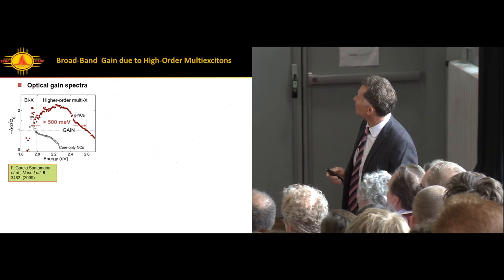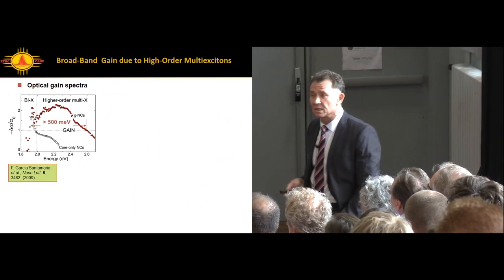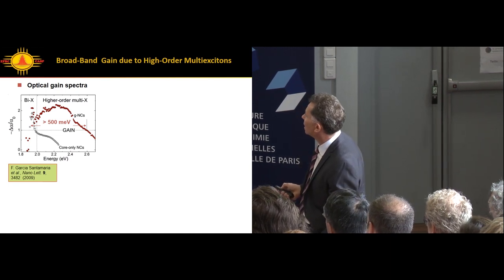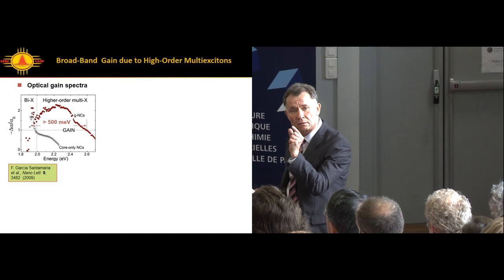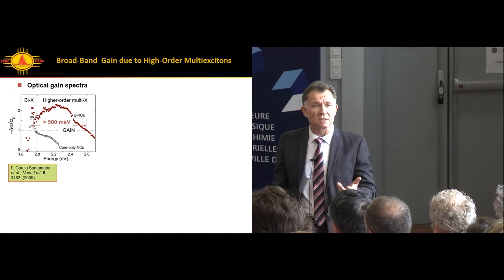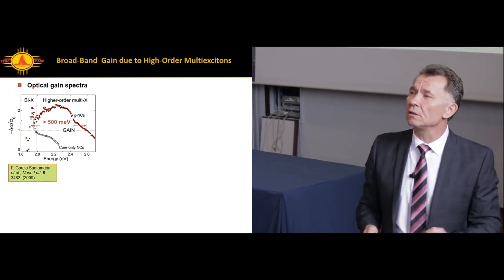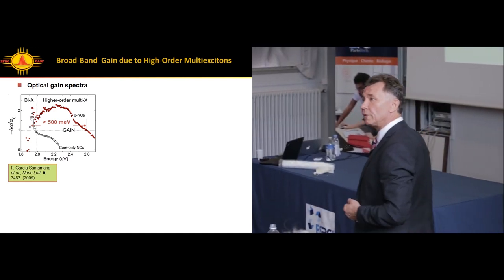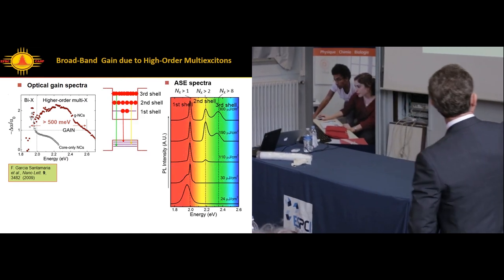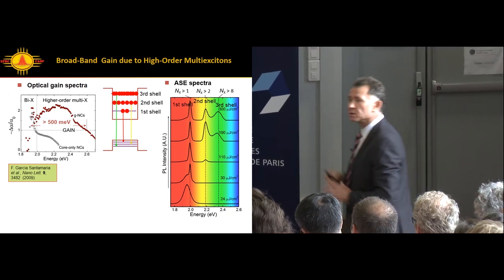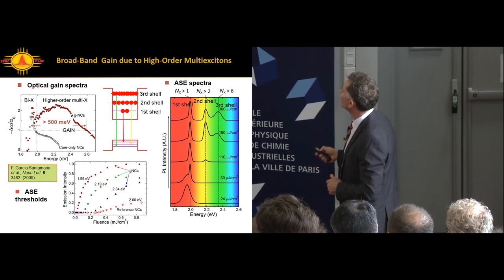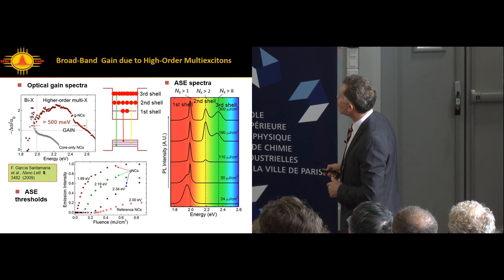Implications for lasing. This is one of my favorite topics. Of course, we tested these dots for lasing. We looked at optical gain. In standard quantum dots, we had narrow band gain due to biexcitons. Now, with these long times, we can squeeze out gains not only from biexcitons, we can squeeze out gain from multi-excitons populating the high-energy quantized shells. This is what we saw. We saw very broadband gain, 500 meV gain. We saw multi-mode amplified spontaneous emission. Multi-mode emission amplification due to three quantized shells.